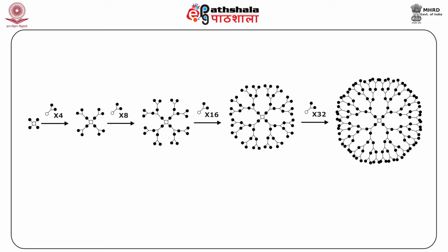At least a coupling and a deprotection step is required in successive additions of each generation, so that growth occurs at a rate of one generation at a time rather than by uncontrolled polymerization. Thus, many synthetic pitfalls are avoided during dendrimer synthesis by using this divergent method. Now, in this figure, it is clearly seen the synthesis of dendrimers by using the divergent method.